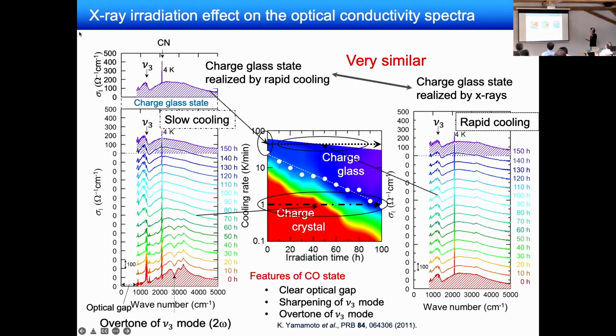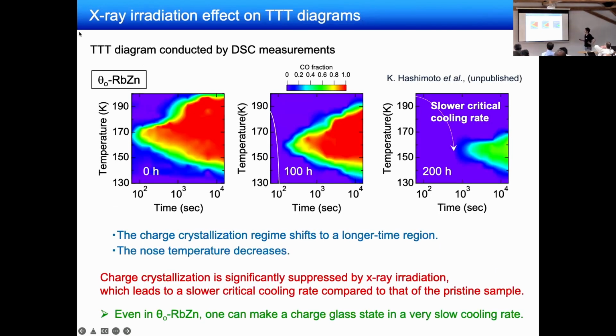And then we also perform the DSC measurement for the X-ray irradiated sample, and we made a TTT diagram as shown here. As you can see, the charge crystallization regime shifts to a longer time region with increasing irradiation, and also the peak temperature decreases with increasing irradiation time. So the result indicates that charge crystallization is significantly suppressed by X-ray irradiation, which leads to a lower critical cooling rate compared to that of the pristine sample.